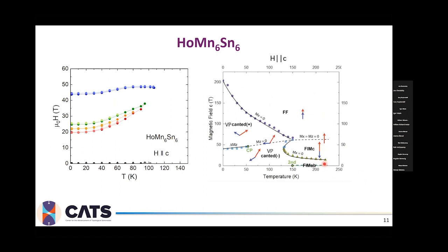So when we look at the experimental and theoretical phase diagram, we again can see that the predicted critical endpoint actually does exist, and I think we are pretty well matched in terms of the magnetic field, because it is around 47 Tesla. However, we do see it at 108 Kelvin instead of 50 Kelvin. So that was a first example which we studied in high magnetic field to investigate the magnetic